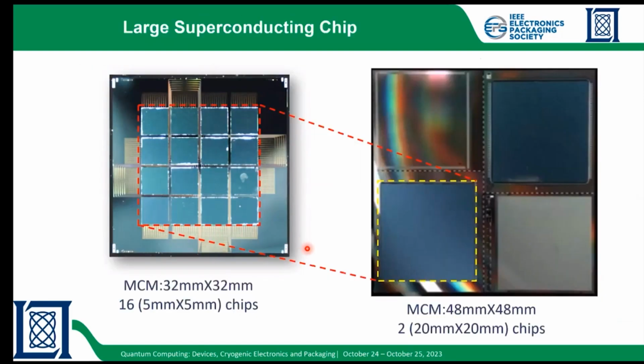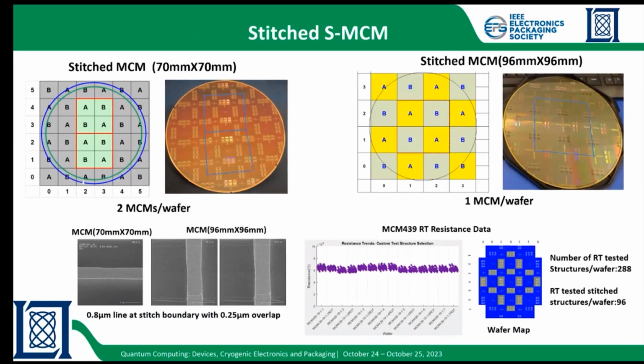So why are we choosing a large superconducting chip? As you know, one 20 millimeter by 20 millimeter chip and sixteen 5mm by 5mm chips will have the same chip area, but the 20mm chip will have a larger active circuit area than 16 individual 5mm chips because it doesn't have edge keep-out area for dicing as well as inline metrology for individual small chips. In general, one 20mm chip can have larger active circuit area than 16 individual 5mm chips for a given lithography.